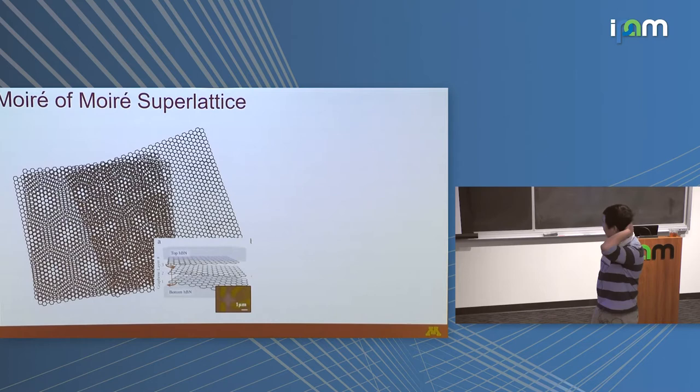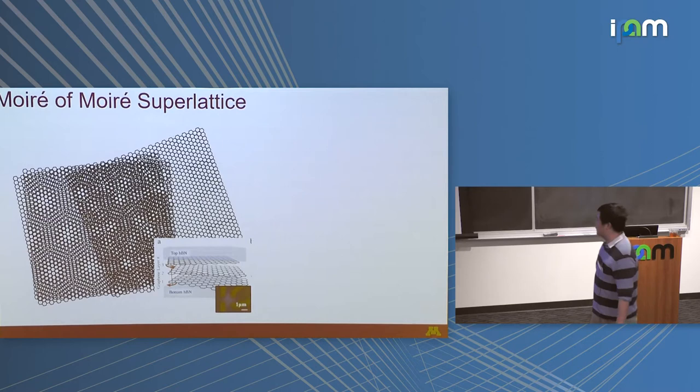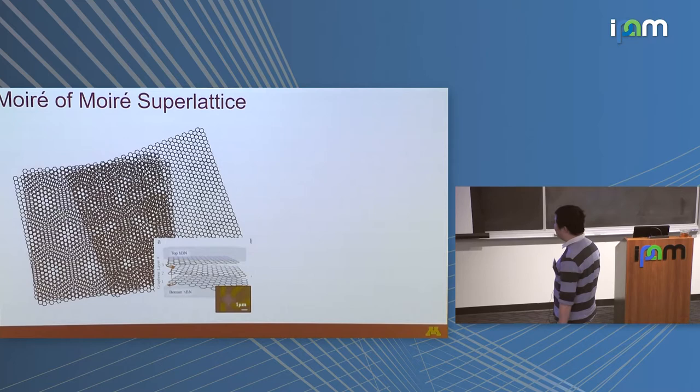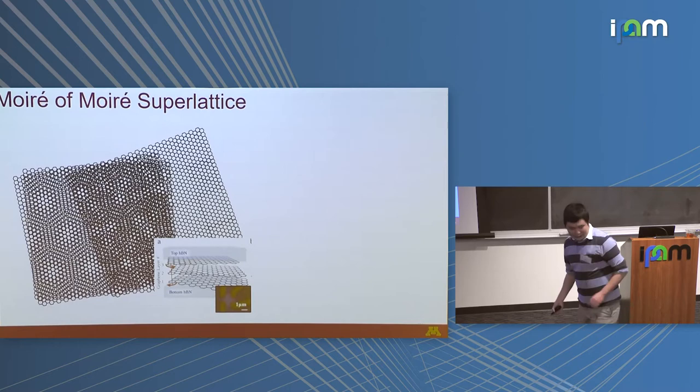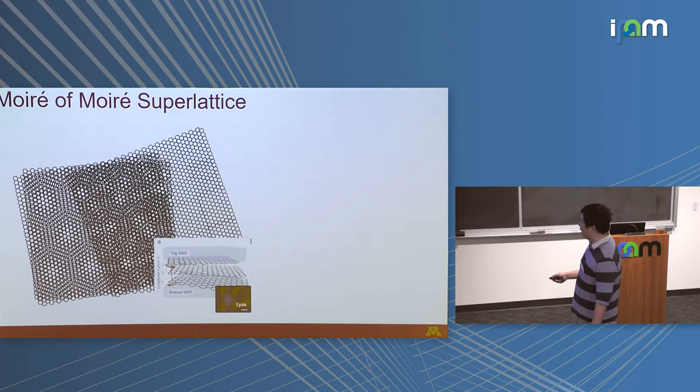And then we just tear it into three pieces so that we know those three pieces have the same lattice direction with respect to each other, and we continuously twist them with respect to each other. The stack ends up being quite big. Through experience, we gradually learned we cannot afford to make the sample too large, because as Andrei also correctly pointed out, there's some angle inhomogeneity. And we found in this trilayer it's, as you would expect, even worse. So in order to see anything with a reasonably homogeneous angle, despite having a very large stack, we need to etch it into different pieces, just on the order of a few microns.